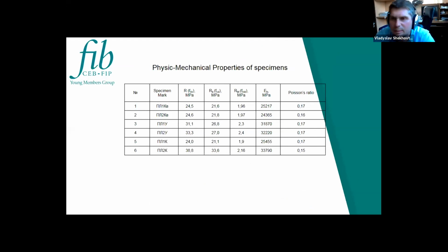Here you see the physical-mechanical properties of the specimens. The series of these experiments was made over 3 years, so unfortunately we got slightly different properties in concrete. It is C20/25 and C25/30. Unfortunately, it is due to the properties of cement produced by our plants in our country, which vary a little bit year by year. So we have some difference in the properties, but we include these differences in our calculation and in our theory.